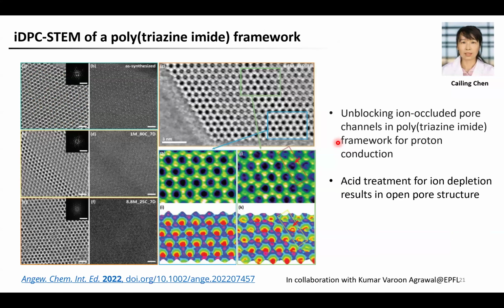And we have also used iDPC-STEM to study organic nanoporous materials, specifically polytriazine imide, PTI. PTI has guest molecules, lithium chloride, in the channels, and these guest components can be removed partially or completely by acid treatment. So through imaging, we provide direct evidence for the removal of these guest molecules from the channels of PTI. As you can see here, some channels are already empty, while the others remain occupied. So this is a very good demonstration of iDPC-STEM for host-guest interaction study.